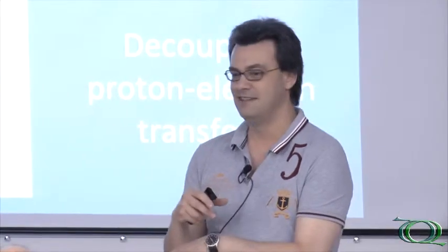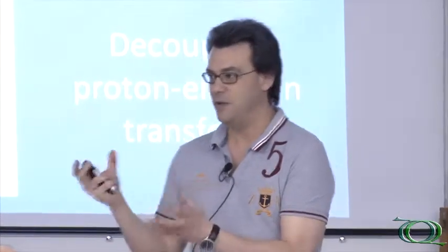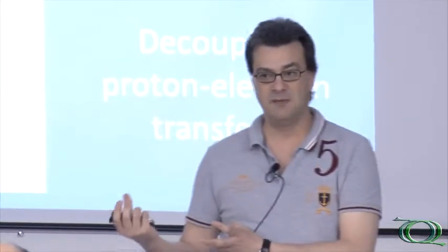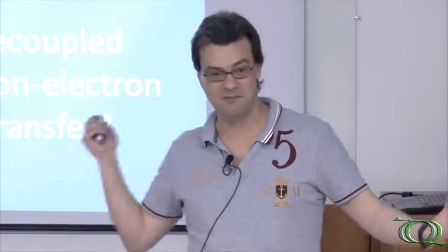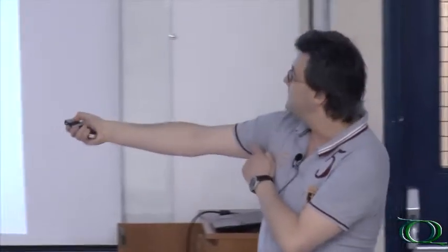Initially, I thought that we could be looking at the decoupled proton-electron transfer. But then I realized that this is nonsense, because what we are doing here is, again, changing delta G of the process. This means that you are changing either the initial state or the final state. And even with the coupled proton and electron, we still have the same initial state and final state. So this explanation makes no sense. I don't know what's happening there, but it's something very interesting that we are provoking a super-Nernstian shift of this peak when we change the pH.